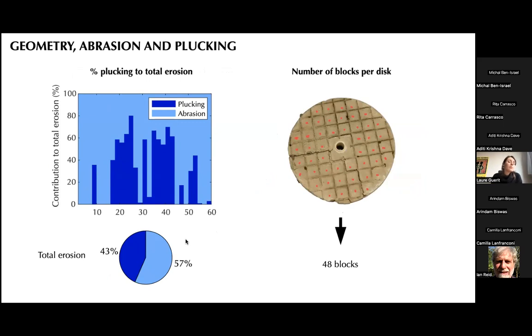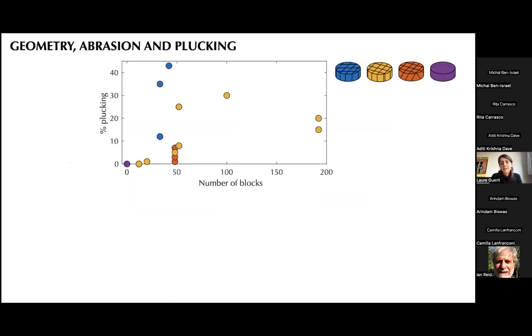So this is a contribution of plucking to total erosion. The other parameter is the number of blocks per disk. So here we simply count how many blocks there are in a disk, and we use it as a proxy for fracture density, because if you only have a few fractures, you only have a few blocks. And this is how these 2 numbers relate.